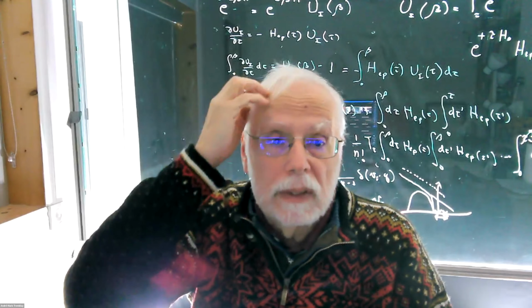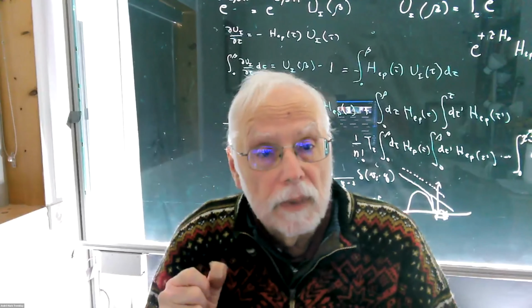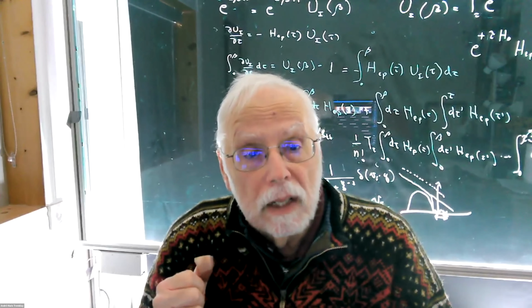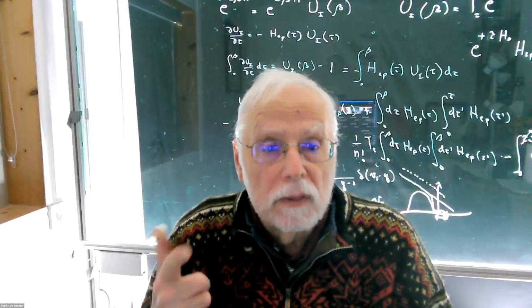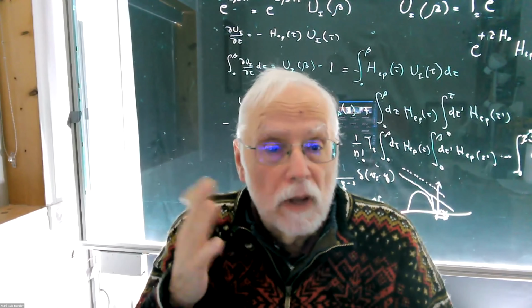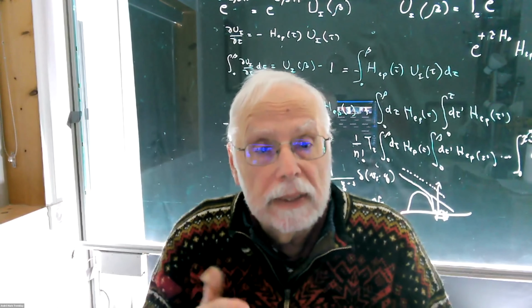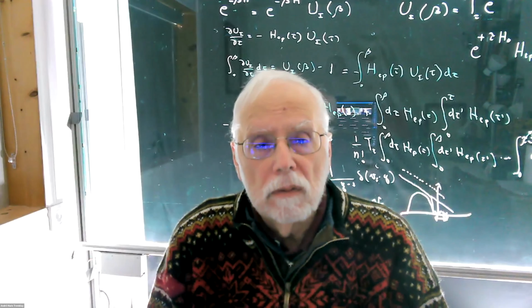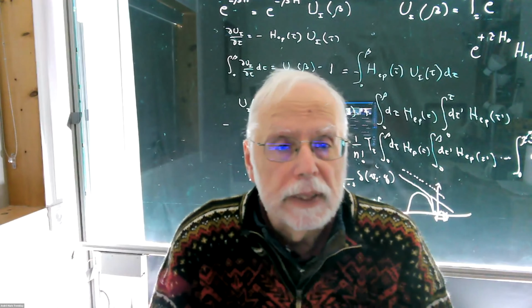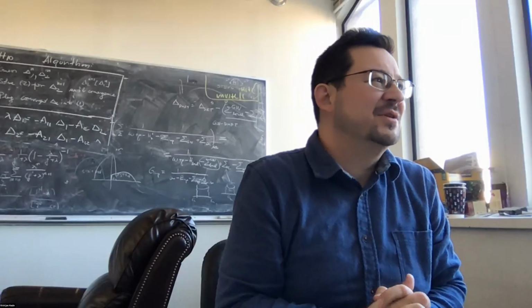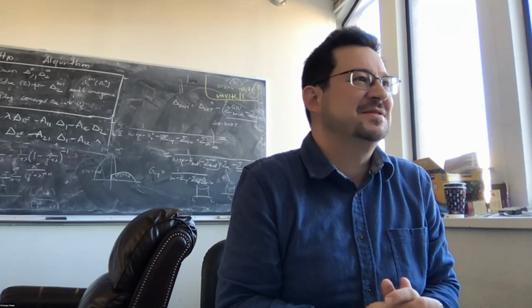One way that the model was reduced here, even in this three-band calculation, is that the oxygen comes in through a hybridization function, because it's sort of non-interacting, so it can be integrated out in some ways. It's still there, you can measure on it, but as far as the many-body problem is concerned, it's hidden in a hybridization function. That's a trick that was used by Christian and Gabby. If you're fine with working with Lagrangians, it's actually not so bad. It's just like you have a Lagrangian for D only, but it has to be a Lagrangian rather than a Hamiltonian.